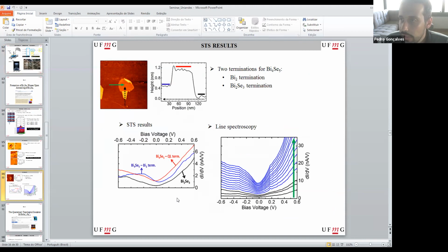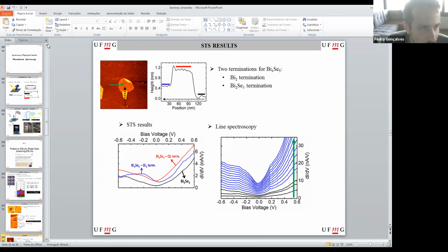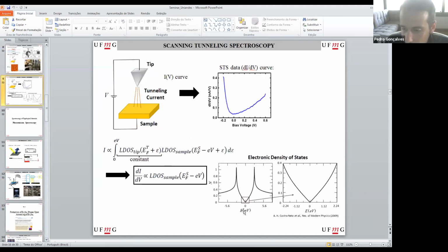So the best way to see the Dirac cone is using ARPES. But if you do have the Dirac cone inside the bulk band gap, you should also see a V curve here, like on the graphene here. You see, you have this V here, which is from the Dirac cone of graphene.